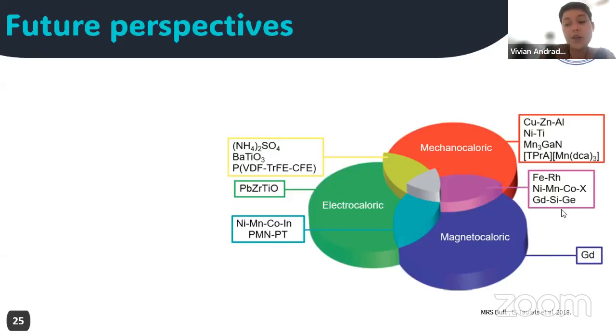Gadolinium silicon-2 germanium-2 undergoes a first order phase transition. So when it changes its structure and comes back, the material breaks. This also happens with the Heusler alloys at the martensitic transition, which reduces the lifetime of the material. So after several cycles, you have a loss.